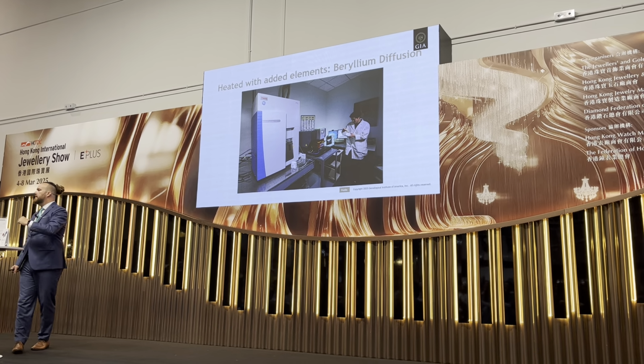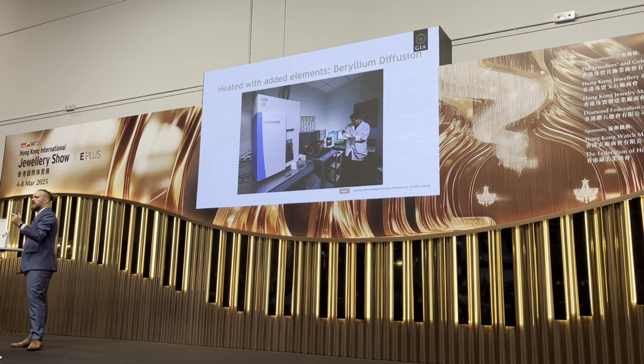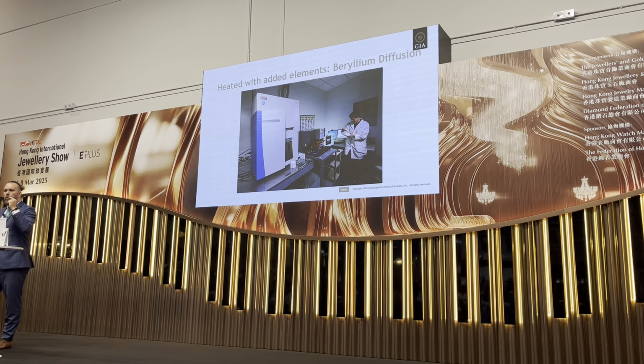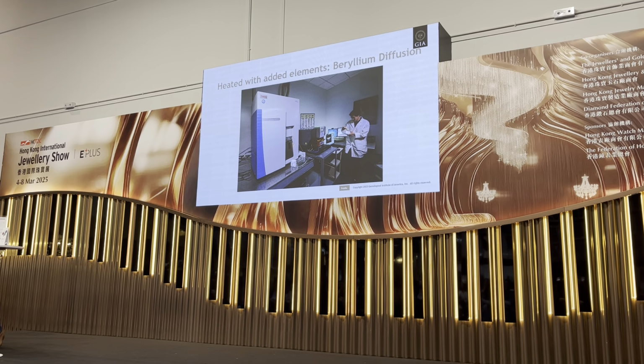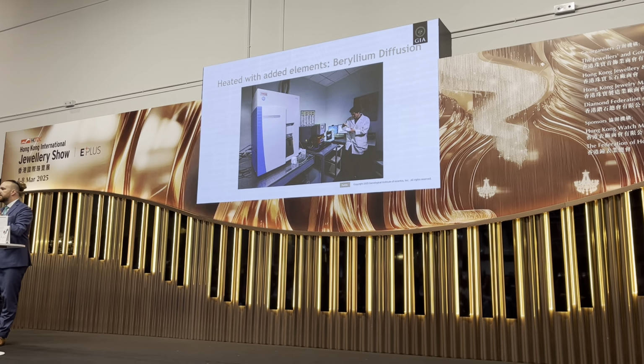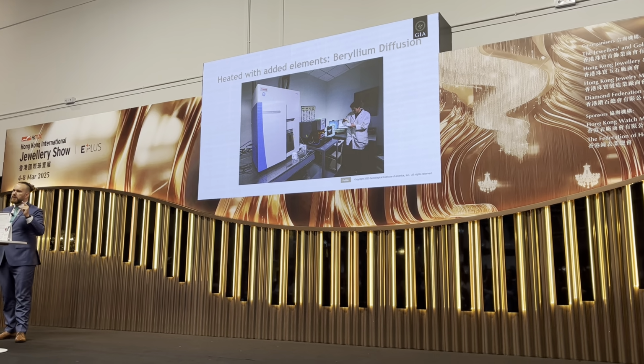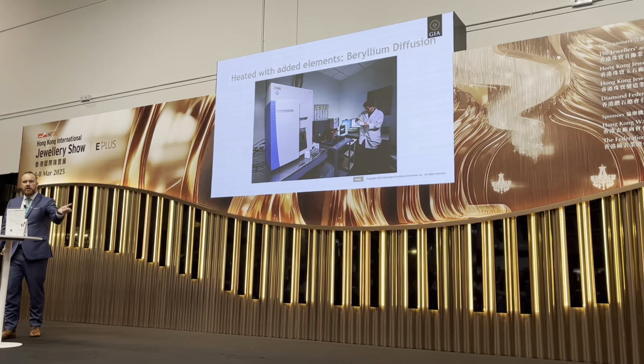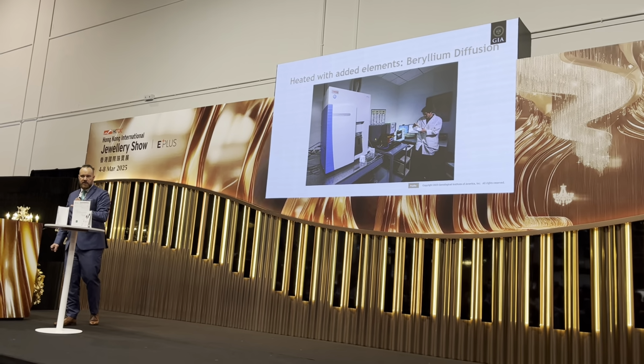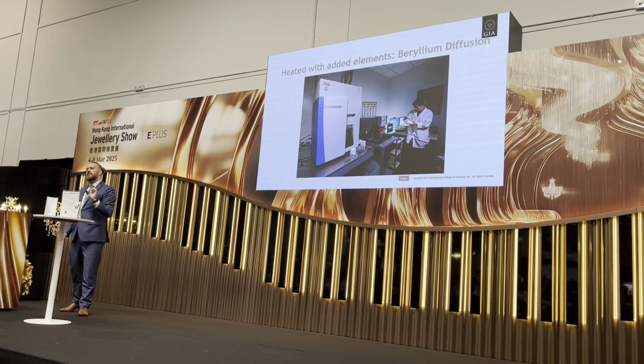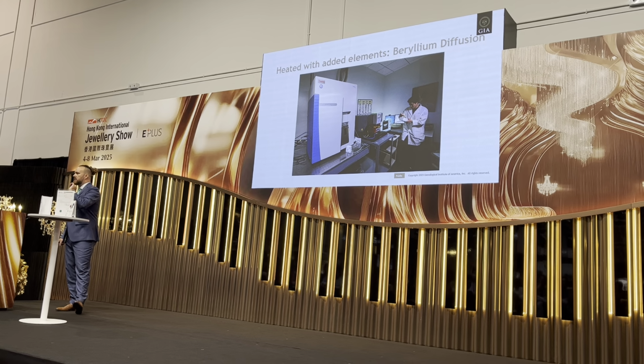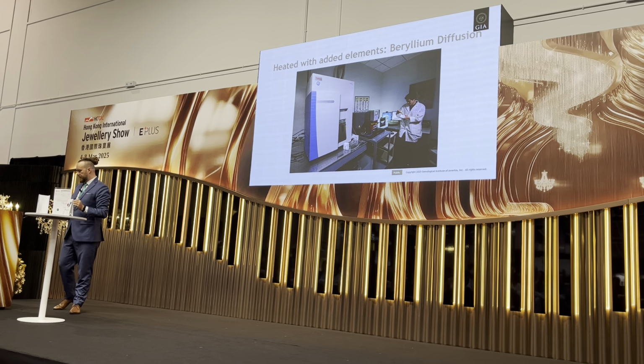And why do we need that good of equipment? It is because 1 part per million, 2 parts per million, 3 parts per million is enough to change your corundum from completely colorless to a bright orange. So it's that little material, that little treatment that can actually have a huge impact on it.